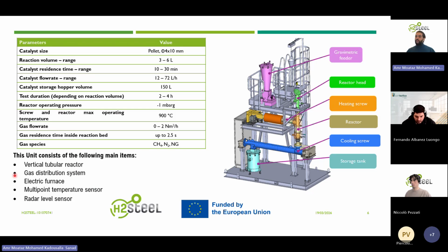Okay, and here is a list of the operating conditions and parameters for conducting an experimental investigation in this plant. The list includes all main parameters from catalyst shape and sizing to available reaction volume range and catalyst residence time within the reactor. As previously mentioned, the plant is designed to operate with up to 2 normal meter cube per hour of gas at the inlet, which can be either a mix of methane and nitrogen or pure methane, and natural gas can also be used.